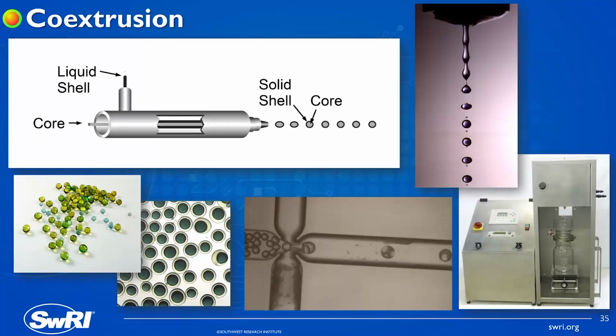Move over to liquid filled core shell capsules. This is where you get into co-extrusion. So this is a nozzle inside of a nozzle where you extrude two liquids to form a liquid inside of a liquid droplet, and that outer liquid then hardens. And then depending on what that liquid is, it could be a melt, a wax, so you're going into a cold chamber and pulling the heat out, or it could be starch or gelatin based, in which case maybe you're adding heat to dry off, or it could be something like alginate, if you're familiar with that, where you're dropping into a calcium chloride bath.